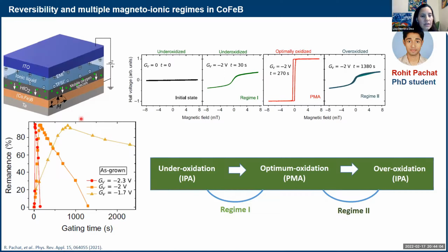So here you can see the plot of the remanence of the loops as a function, once again, of the gating time at a given gate voltage. Well, the first thing you can see is that, of course, if you increase the gate voltage, things start happening much, much quicker. So that is a normal observation. But you can see as well that we have these two branches, right? We have the first branch, which corresponds to regime 1, so going from in plane to perpendicular, which is the high remanence state. And then we have a second branch going from PMA back to in plane, right? That is regime 2.